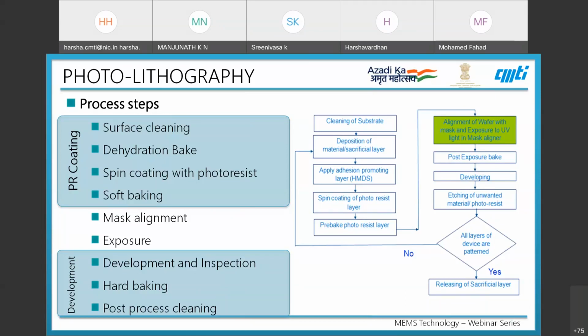After the alignment is done, there is a post-exposure bake, followed by the developing process. After developing, etching of unwanted material or removal of photoresist is required to arrive at the desired pattern. This entire flow has to be maintained for one layer of the device.